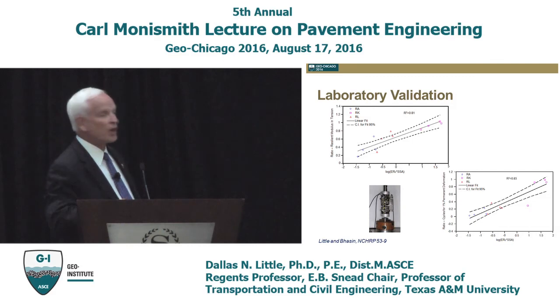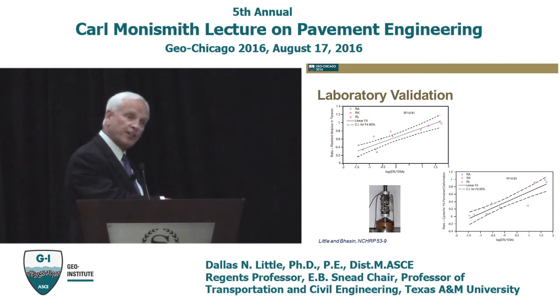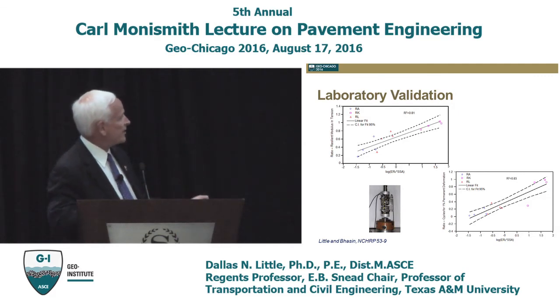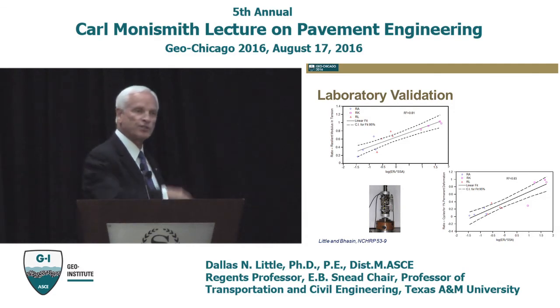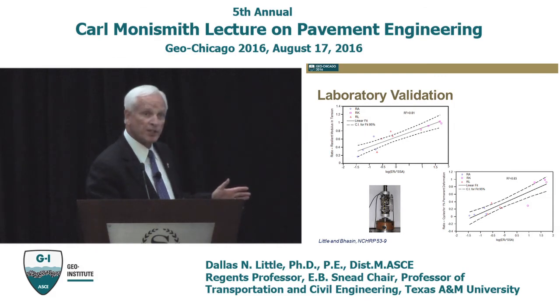Here's a little data that just shows you that we can actually validate that that's the case. This is the ratio of resilient modulus in a wet state to the dry state. Of course, the higher that value, the better it is. And this is the log of that energy ratio. So you want that number to be high. As that number is higher, you can see that the ratio of the wet resilient modulus is high compared to that of the dry. When that ratio is low, it's low. And these are 95% confidence interval bands, the dashed lines. So it looks like it's pretty good data.